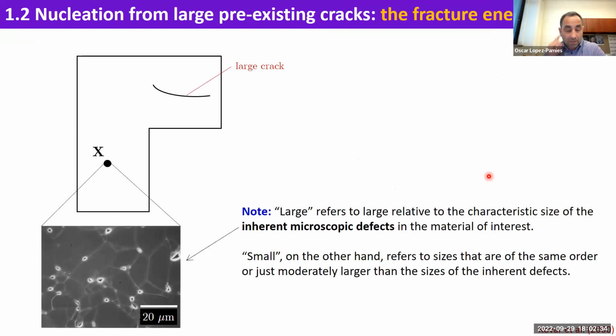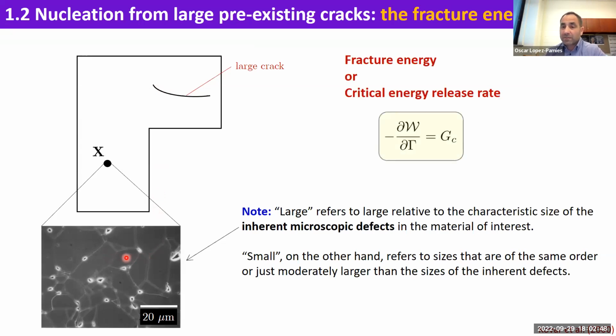Then from a large persisting crack, now this is well known, and this is Griffith fracture. By large, I guess I'll point out the following: materials, when you look at them with a microscope, have defects. What large means is that this crack has to be much, much larger than the inherent defects. And if that's the case, we know from experiments when the crack is going to propagate, when it's going to nucleate from the crack front that is pre-existing. And this essentially is given by this formula. If you're familiar with it, that's fine. If not, it's a different criterion than the strength criterion, right? And this is, again, well known from experiments.